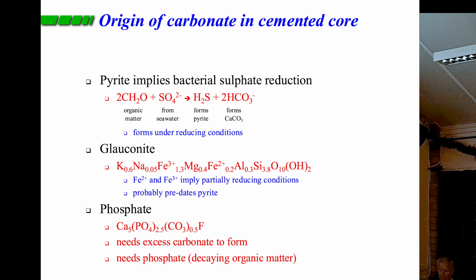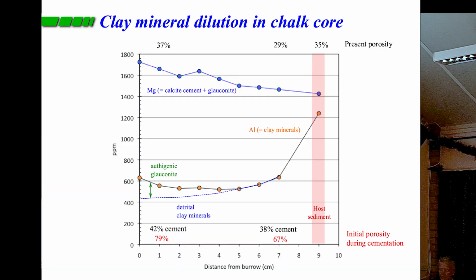And it contains calcium phosphate here, and the phosphorus probably comes partly from degradation of the pogonophore and also partly from decomposition of things like fish scales which are around in the area. But I know all of these are going on in the central chalk core. So what we can do is look at the chemistry of what's happening in this chalk core.